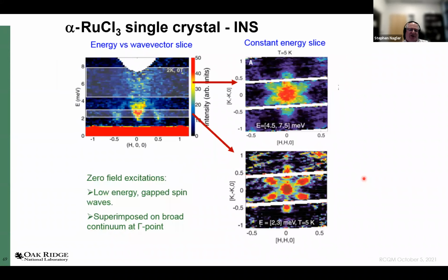And if I look at this more closely, now I'm plotting one direction in reciprocal space here and energy vertical. And you can sort of see the shape around what's a 2-dimensional gamma point. Now, I should point out, in order to do this, we have to sum over some non-zero range of momentum perpendicular to the A star B star plane here. So we're looking at something that we're assuming is quasi 2-dimensional, which turns out to be a pretty valid assumption. And then if I look at low energies, I see this thing here with well-defined cones and a piece in the middle. And at higher energies, I see this kind of Star of David shaped scattering. Okay, and there's a broad continuum at the gamma point.